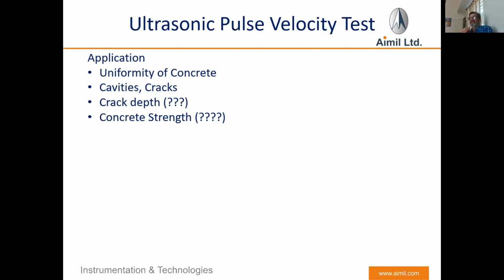Concrete strength, again a question mark. Nowadays there is research going on about correlating the compressive strength with the velocity of the concrete, that is the pulse velocity. But still there are differences of opinion. Sometimes people say velocity and concrete strength are two different parameters which cannot be correlated, but some people say there can be some correlation. We do not have a complete correlation between these two parameters. Probably after 5 or 7 years down the line we may have such a correlation, but right now, no.